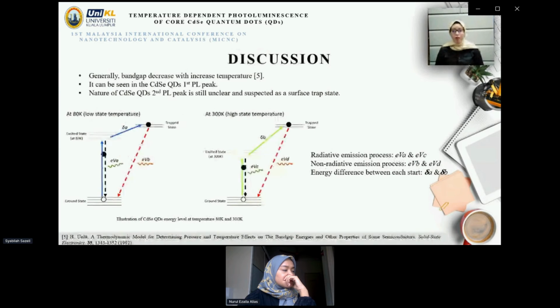This is the illustration of energy levels for cadmium selenide quantum dots at two different regions. EVA and EVC represent the main radiative emission process. EVB and EVD represent the non-radiative emission process. Delta A and delta B represent the difference between energy levels from ground state to excited state. This suggests that the radiative emission originates at the first PL peak, while the second PL peak is from non-radiative emission.